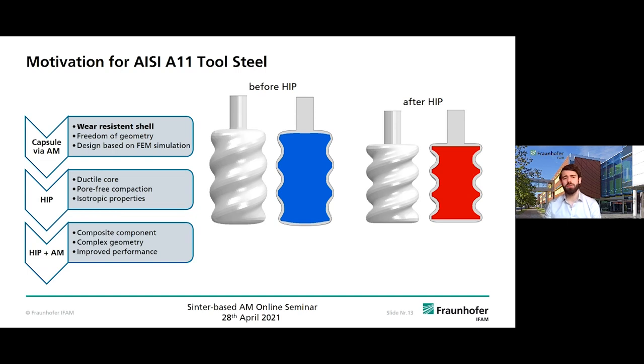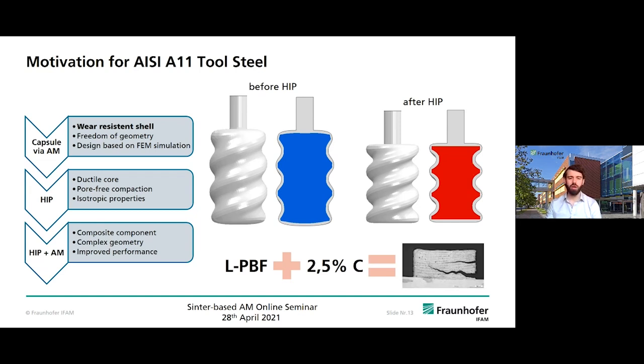In the beginning, we started with laser beam melting, and a lot of carbon results in a cracking material. So this was not a suitable process for this material. So we started working on it with binder jetting.